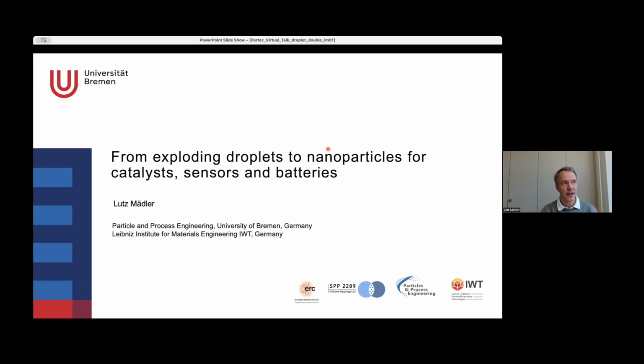And sensors is also a word here. Gas sensors are electrochemical sensors that work basically on this: if you have a gas and it reacts on that material, it changes the electron density, and you can measure that electron density if you put a current through the particles with two electrodes. The really nice thing about the sensors is that we deposit our active sensing layer directly on the interdigital electrode of those sensors. So there's no step in between. It's all dry. We just spray that on these sensors and then they are done. It's quite nice for these applications.